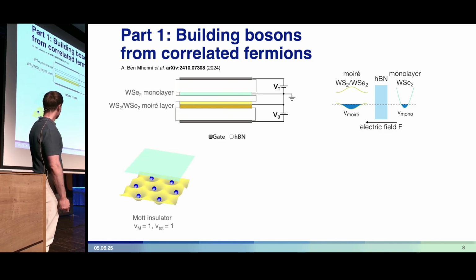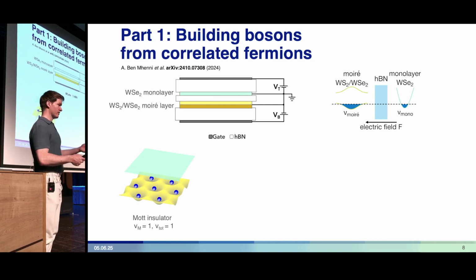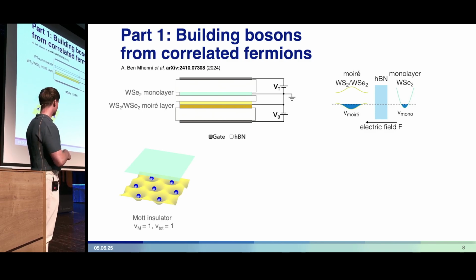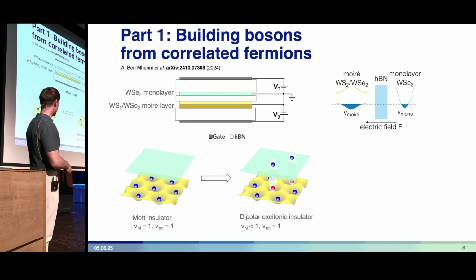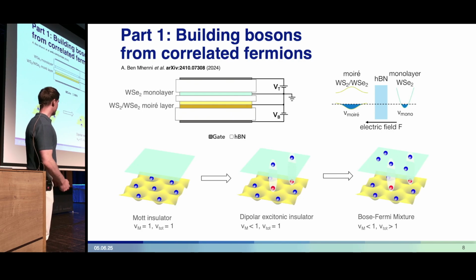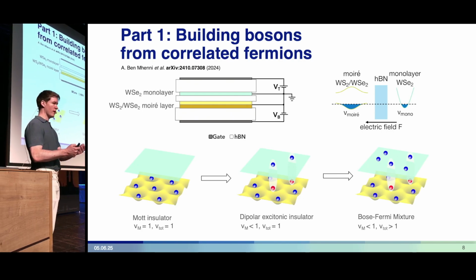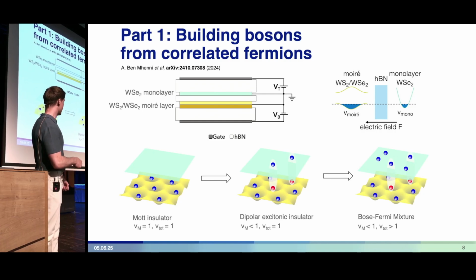Using these different controls, the electric field and chemical potential, I will show you that we can realize a few different kinds of correlated phases. The first is a Mott insulator consisting of electrons residing in the Moiré layer. Then I'll show you that we can modify this Mott insulator by pulling some charges from the Moiré layer into the monolayer to form bound states, interlayer excitons, forming a dipolar excitonic insulator. Finally, this dipolar excitonic insulator is actually robust to charge doping, and we can form a Bose-Fermi mixture.